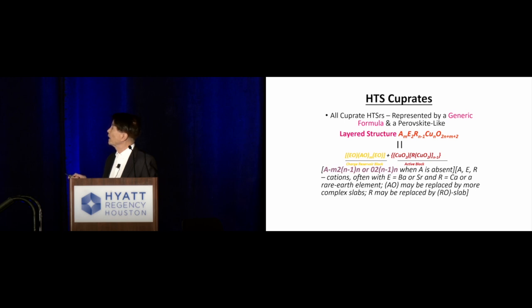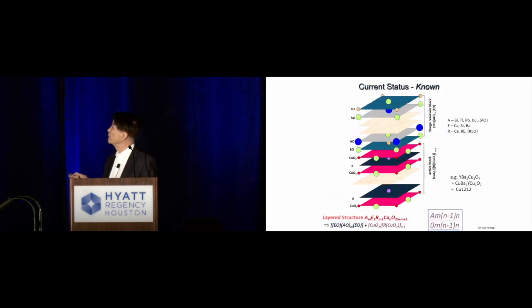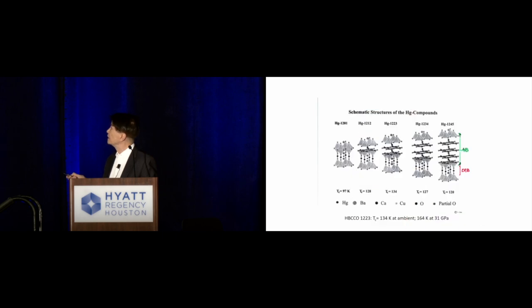Then later on, we continued to work on this class of material and refine its structure and also physics. And as you can see, it turns out they're all layered compounds, and all these layers can be grouped into 2 blocks. One is, I call it, the charge carrier block, and the other is the active block, which consists of copper oxygen layers. And these are the active layers. And so later on, many other compounds also with this structure were found superconducting.